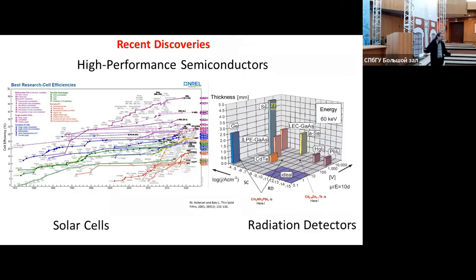So you know Halide Perovskites, and the reason you know Halide Perovskites is basically this chart over here. This chart shows the established solar cell performances of materials. Halide Perovskites are here, this curve line. There was tremendous progress in the beginning of the field. Now it's starting to stabilize, but again, the performance is very close to that of silicon. So these are good materials to work with, and people are excited about it. But we're plateauing here, we're getting a peak. So why are we looking at these materials?